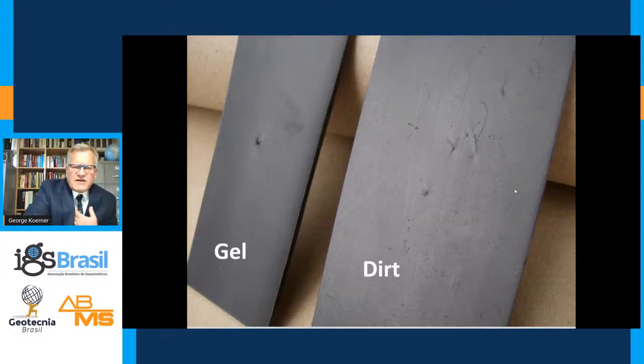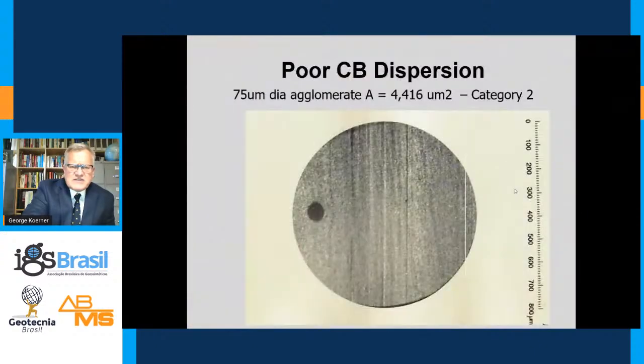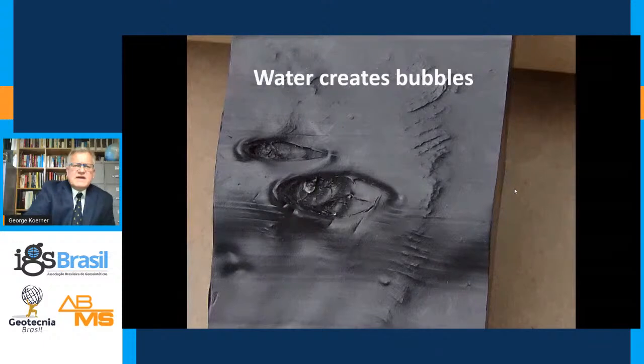In regards to textured material, if you're not cleaning the die lip, you can have excess material, which can agglomerate on the texturing surface and give problems. You can have gels or dirt inside this. The screen is not working well inside the extruder, and these foreign materials enter the sheet, which give problems and rise to stress cracking. You can have problems with carbon black dispersion. These big carbon black agglomerates are problematic and certainly need to be taken care of. If you have water with a lot of humidity or a problem with water dripping on the equipment, it can bubble the material and cause problems.